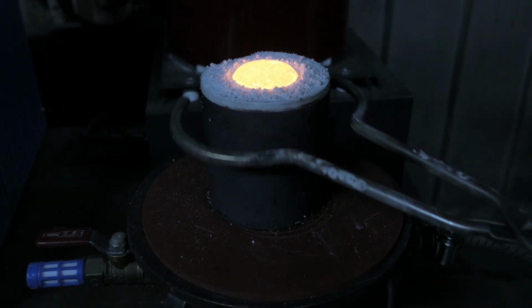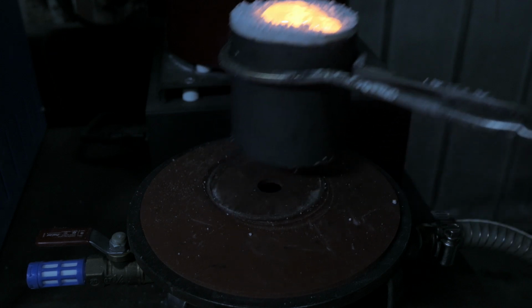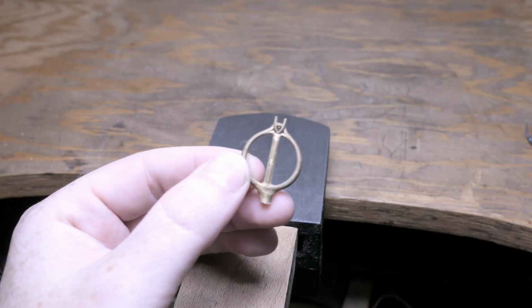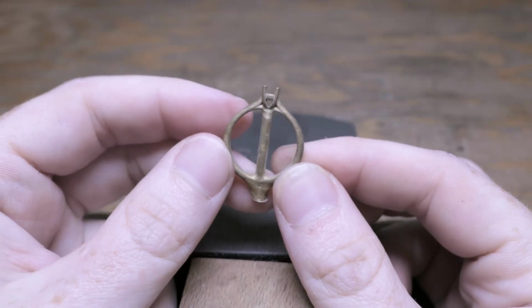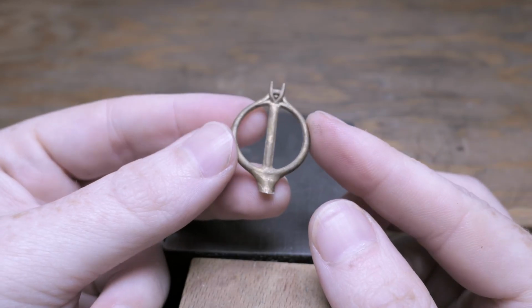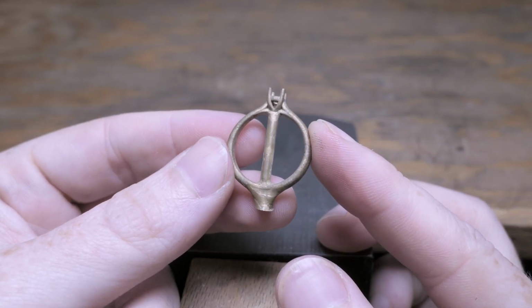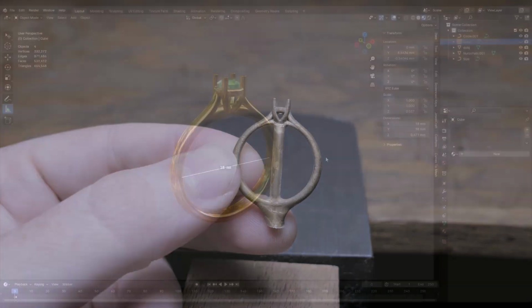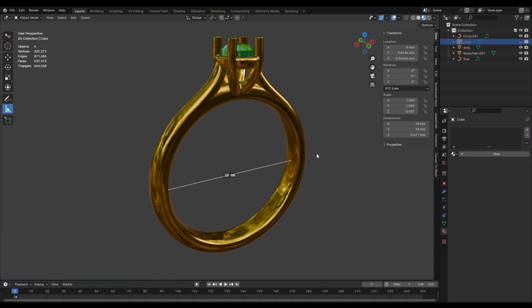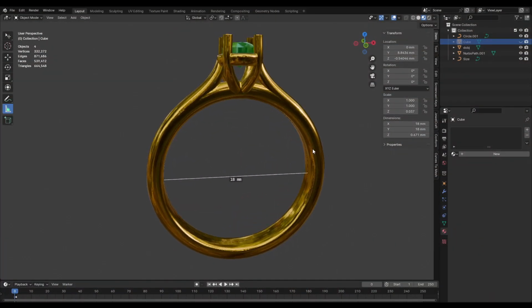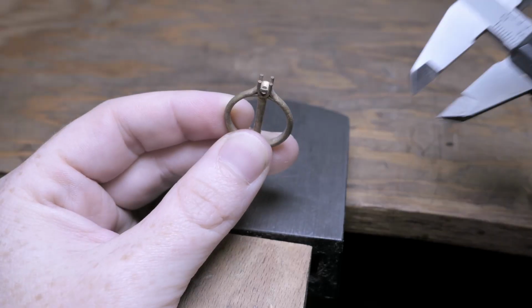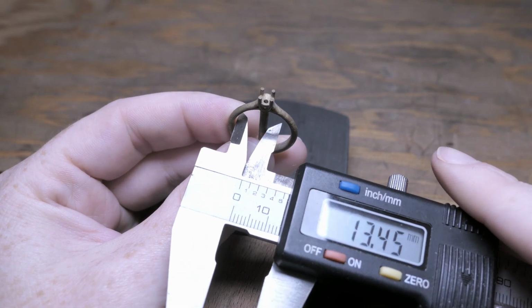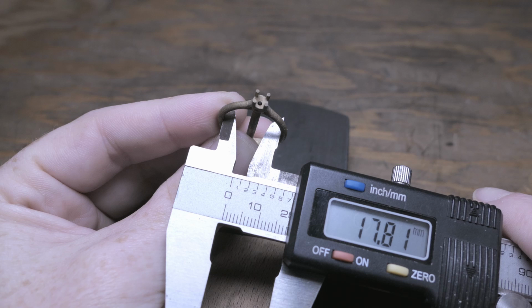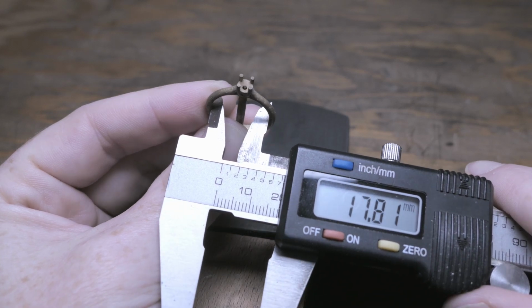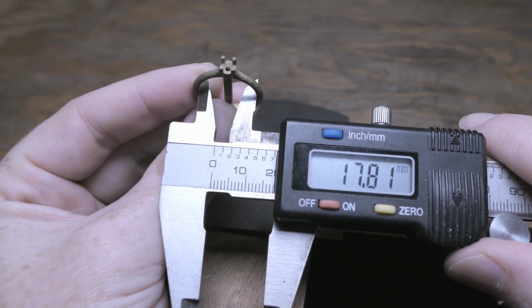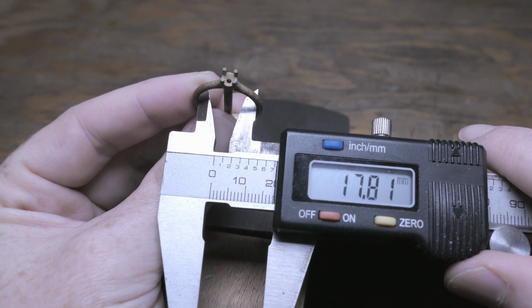So after quenching the flask and doing a little bit of cleanup, this is the raw casting that I was left with. And now I can measure it and see the difference between this casting and the original model. And the ring size that I was shooting for was about 18 millimeters in diameter. And the final casting came to 17.8 millimeters in diameter, which means it only shrank about 1.1%, which is really crazy.